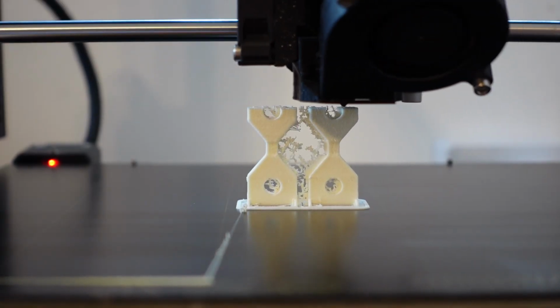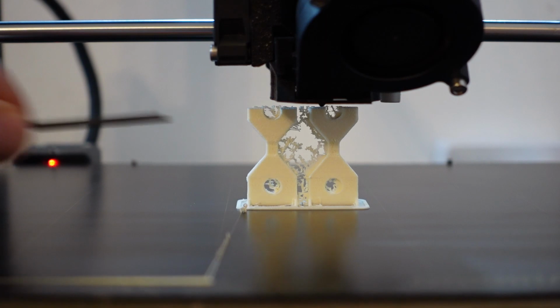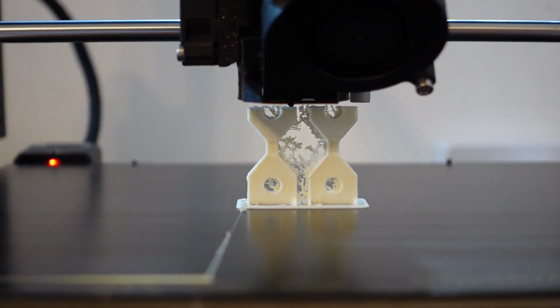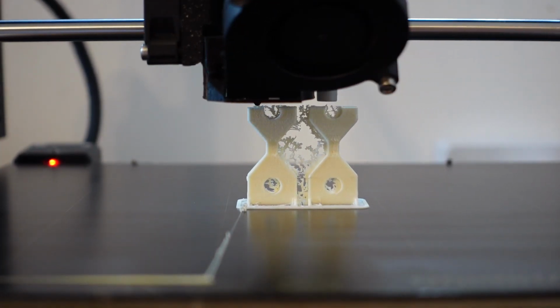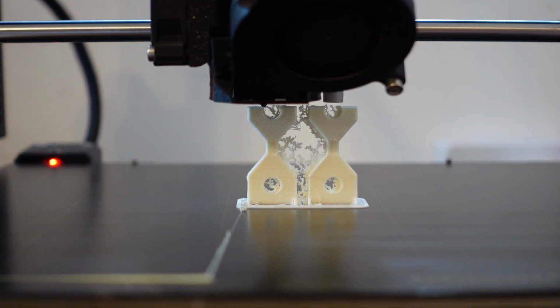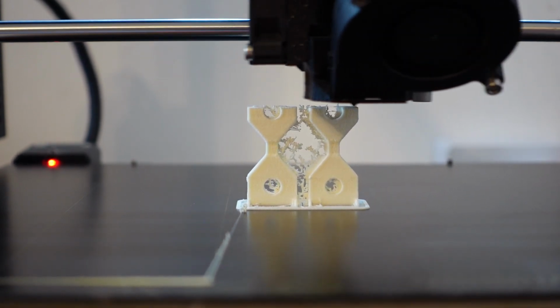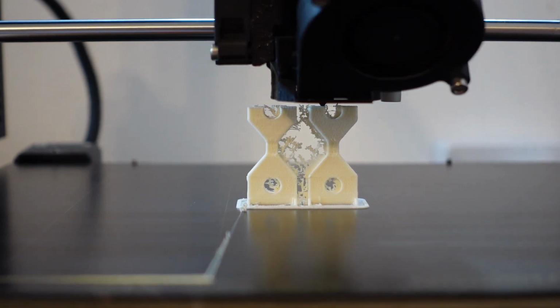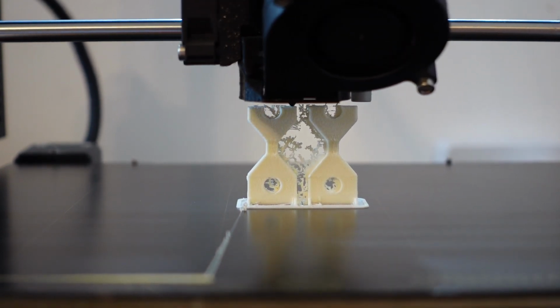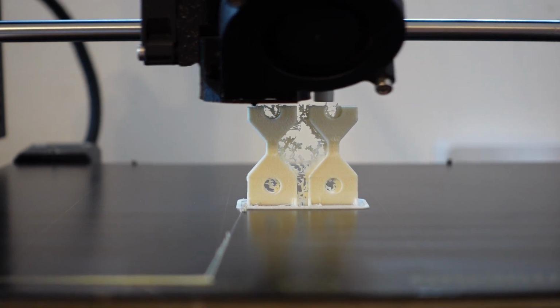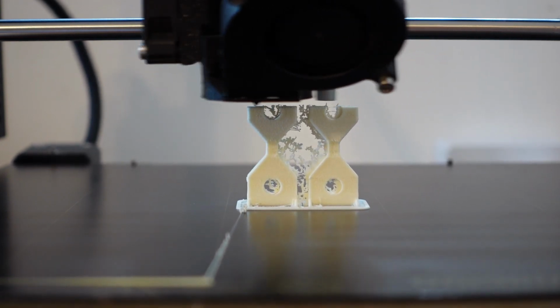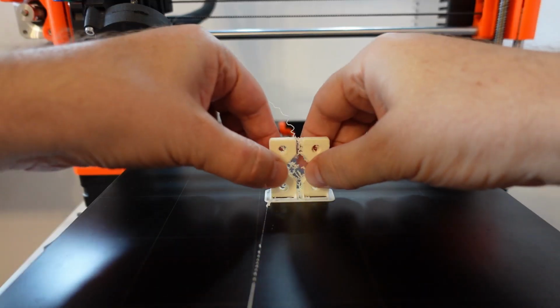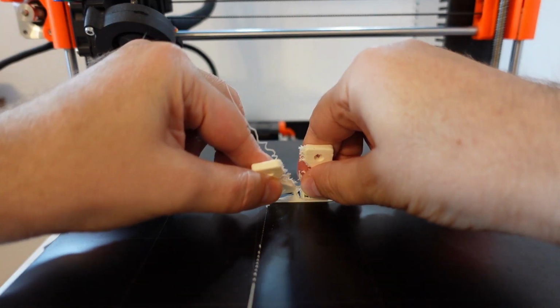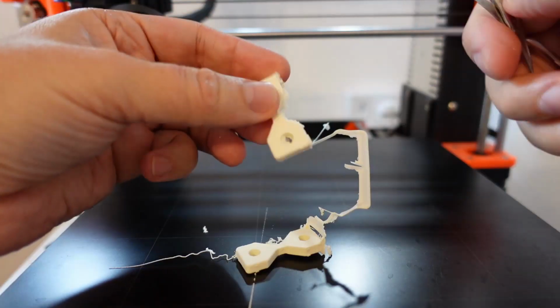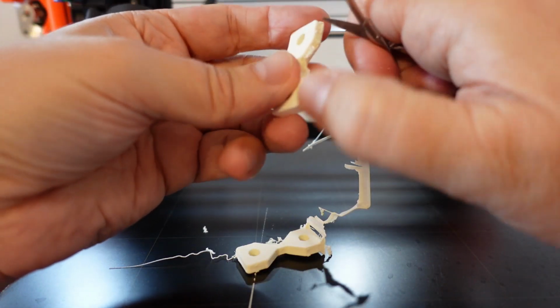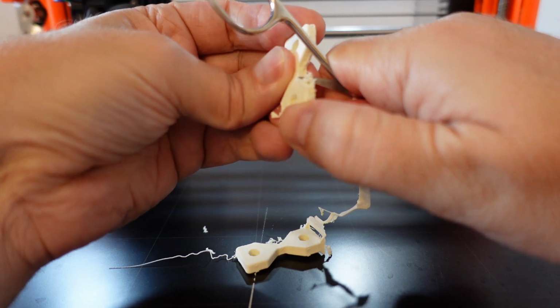And these are my test specimens for the layer adhesion test. The smallest cross-section area is 4 by 4 millimeters. And these are now my standard test objects for layer adhesion, so the results are comparable with the other materials, for example with PLA+. And as I expected, a lot of stringing can be visible here, but this is something we cannot avoid. But it is very easy to clean it at the end. First I remove the brim and now these strings.